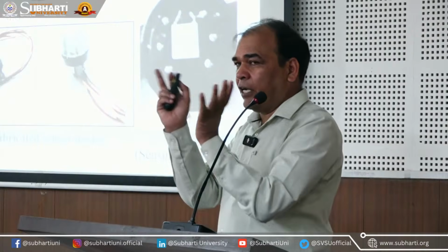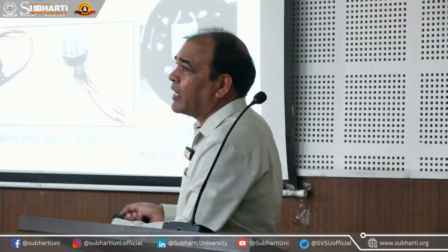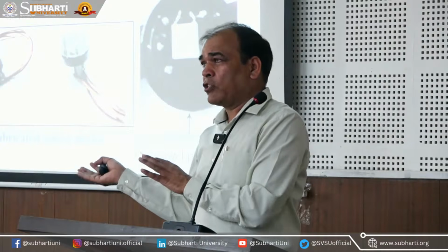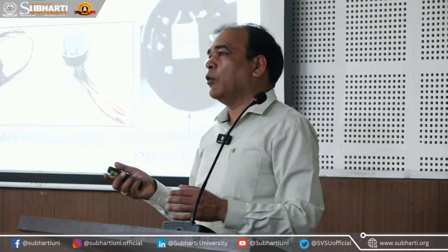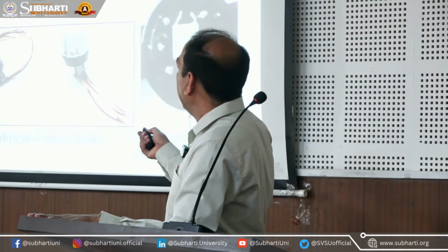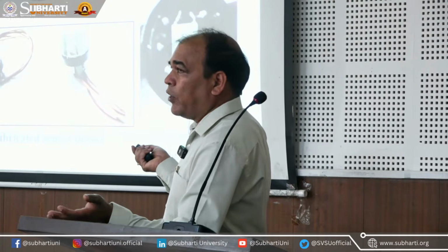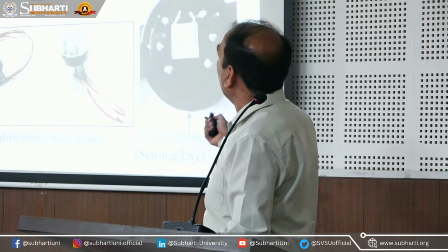This is, as I told, the schematic diagram of the device structure. For this we also need the micro heater. As I mentioned, the oxide sensor will work at some elevated temperature like 100, 150, 200. For that, first we have developed the micro heaters and tested them up to 600 degrees or higher temperature, and then we deposit the materials, and over that we fabricate the interdigitated electrode.